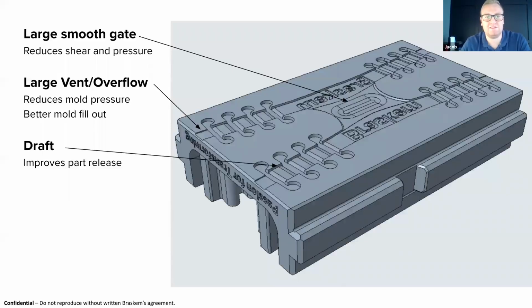So what that allows us to do is two things. We can reduce pressures, but if we have uneven flow, non-geometrically balanced flow within our cavity, and say one side's filling out more than the other, instead of ramping up pressure to help get better fill on the other side of the cavity, we can simply overflow the one side of the cavity to enable the other side to continue filling. And then as Mark said in the previous slide, draft.